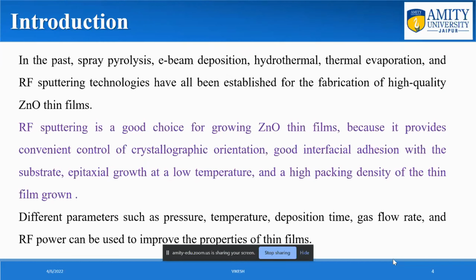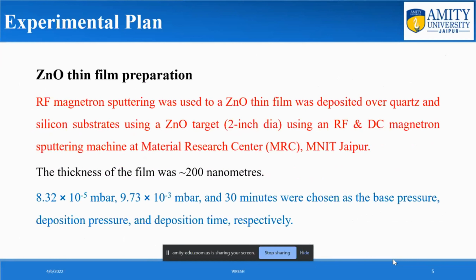Here is the experimental plan, starting with ZnO thin film preparation. RF magnetron sputtering was used: the ZnO thin film was deposited over quartz and silicon substrates using a ZnO target about 2 inches in diameter, on an RF and DC magnetron sputtering machine at the Material Research Center in MNIT. The thickness of the film was about 200 nanometers, and 8.32 x 10^-5 millibar, 9.73 x 10^-3 millibar, and 30 minutes were chosen as the base pressure, deposition pressure, and deposition time respectively.